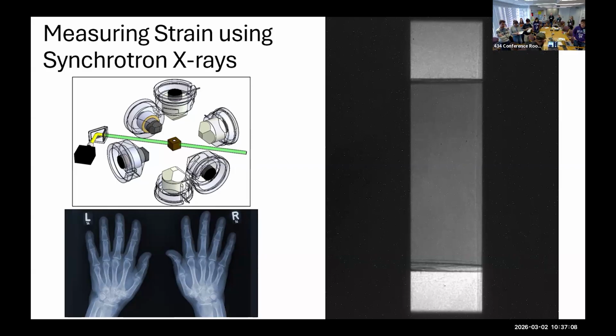So in order to collect our radiographs, we have this scintillator and a camera in place. So this scintillator thing, all it does is when it gets hit by an X-ray photon, it generates an optical photon that can get picked up by our camera. So basically the X-rays that come through here are just going to form a picture on this scintillator, and then the scintillator is going to be fed in the camera. But one of the nice things about it is that we're focusing on the scintillator, not on the sample. So we could move this around and it wouldn't change our image at all. We don't have to refocus. We just focus once onto the scintillator, and then we're good to go to collect radiographs.